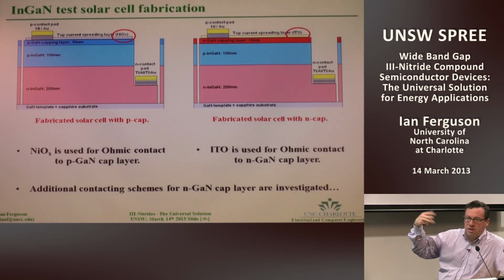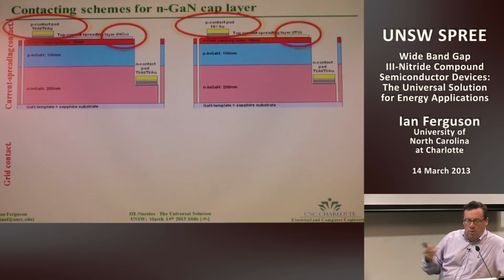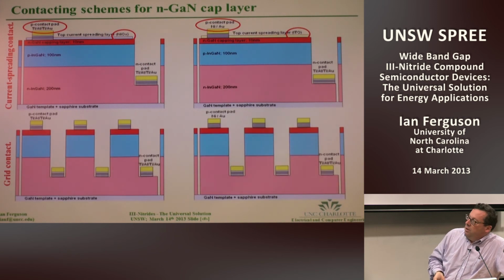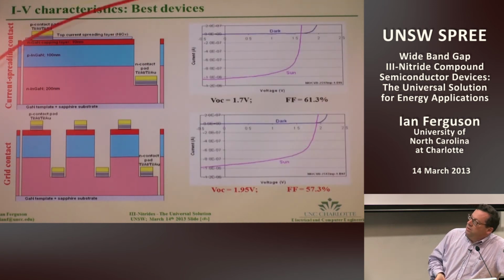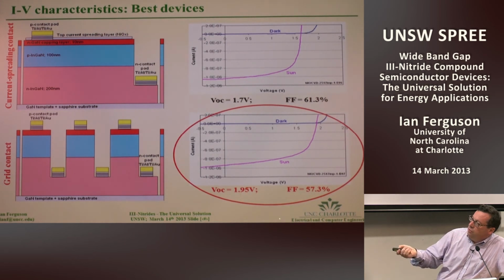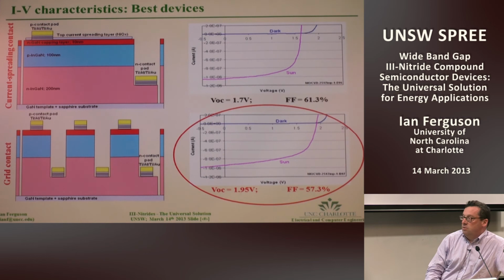We also did some solar cells on silicon, and we also did homojunction cells. But we went through and optimized these layers, and in our final devices we were seeing VOCs of about 2 volts. We had devices where the VOCs were higher, fill factors about 60% or so. Typically, you find the current is low, right? Because there's not a lot of photons around in the ultraviolet, and you're finding that these devices, in terms of these high efficiency tandems, are supposed to add about 6% to the system or so.